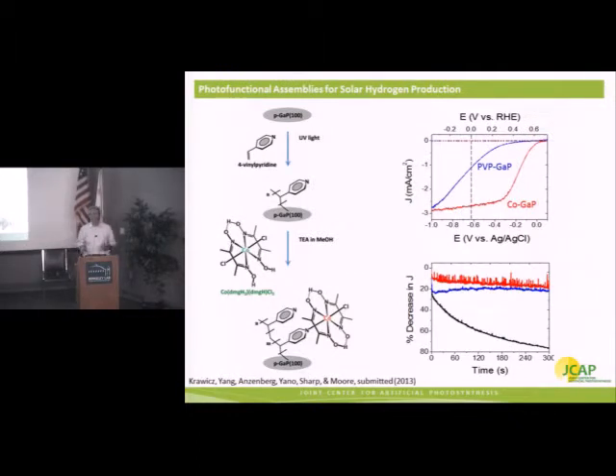Our goal is to do more than just create these constructs and synthesize them. We also need to demonstrate functionality and stability. So up till now, I've shown no current voltage characterization or photocatalysis curves. Here I show on the top right, though, the current that we obtain under photoillumination as a function of the applied potential. The dashed lines on the top show how these photoelectrodes operate when there's no light illuminating them. No current passes the interface.